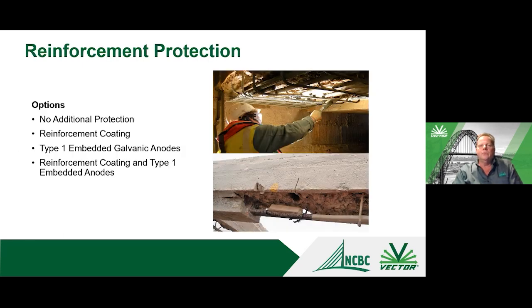So then what you do for the reinforcing protection, if you just follow those procedures that we talked about, you're going to have very clean steel. You're going to be coming back with high quality concrete or mortar, fully encapsulating the bar in that area. It's going to be a chloride-free material, fresh material, highly alkaline. The steel itself is going to be very durable. In fact, I would posit that should be one of the last places that actually deteriorates in the structure: the repair. The repair should be more durable than the surrounding substrate concrete over time.